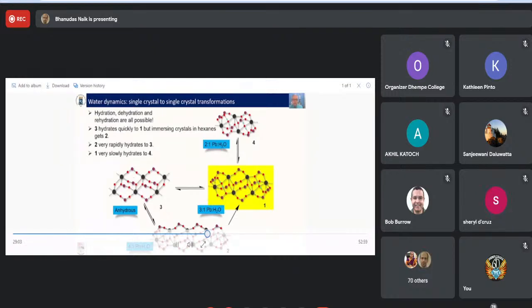If you're really careful, in this case we use just dry hexanes, and this compound managed to pick up water from dry hexanes. It's now in the 4-to-1 ratio, and this quickly goes to 3 if you have more water, and this can go to 2. So this has an equilibrium depending on the humidity. This is a really interesting system.